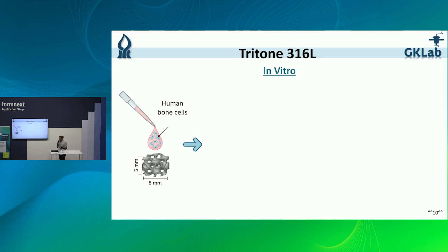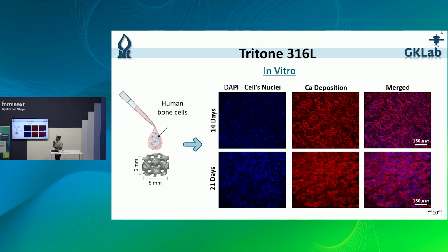The in vitro evaluation included seeding of human bone cells on printed lattice samples and following incubation for several time periods up to 28 days. At the end of the incubation periods, the bone formation was evaluated using fluorescent staining. Here we can see microscopic images of lattice samples that were incubated for 14 and 21 days. The blue DAPI staining, which represents the cell nuclei, indicates the cells' attachment to the surface of the samples.